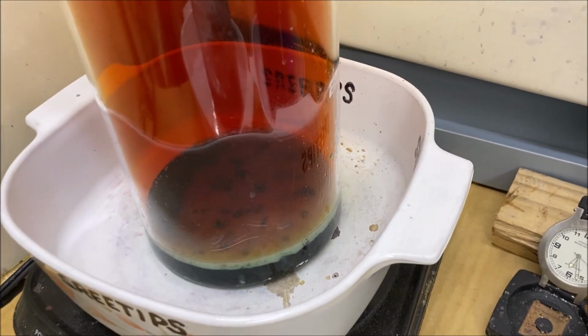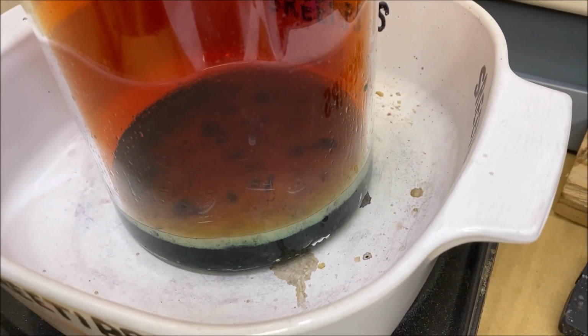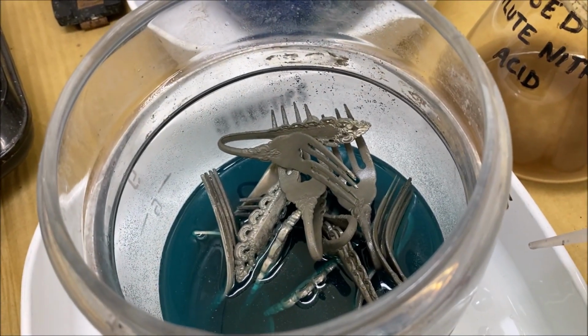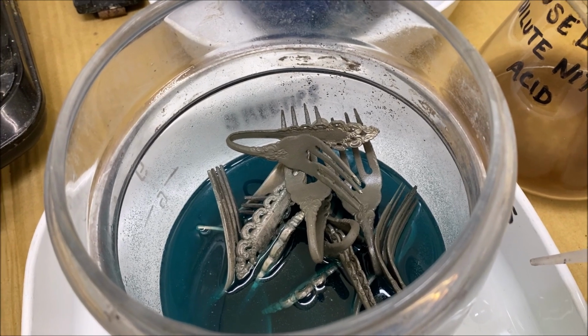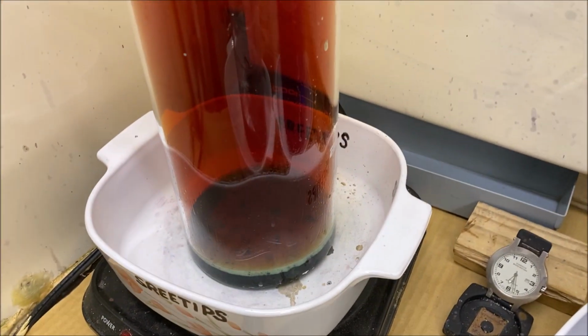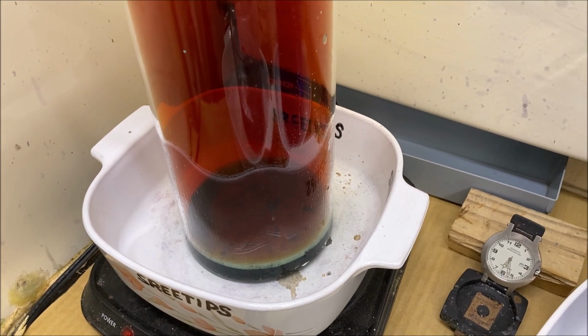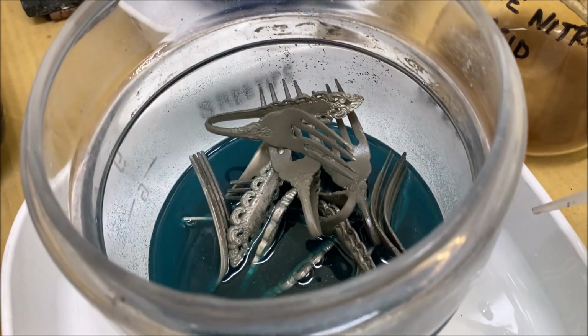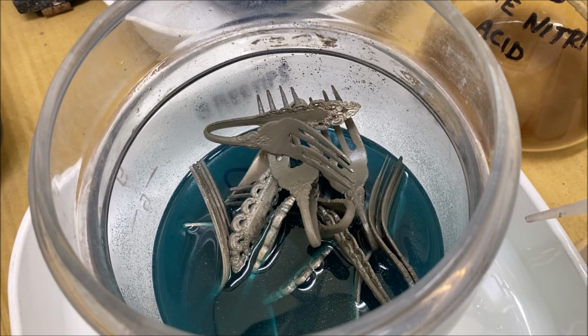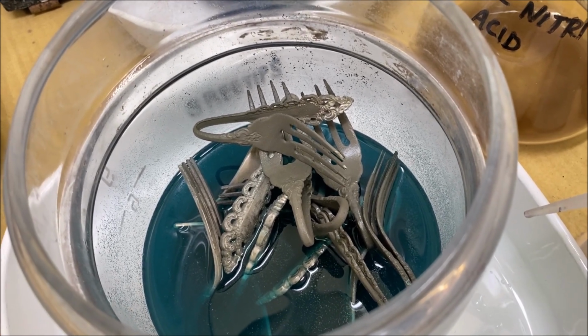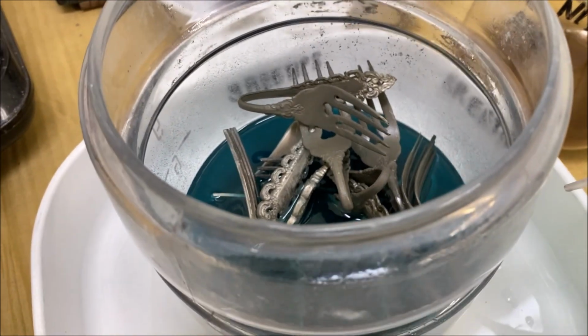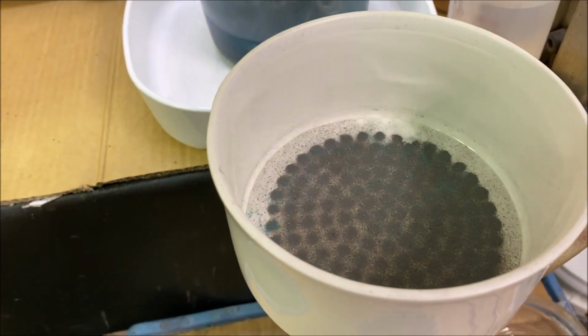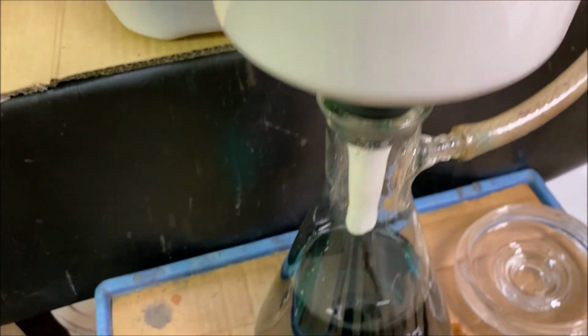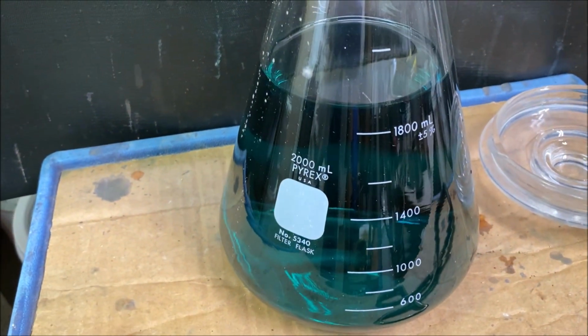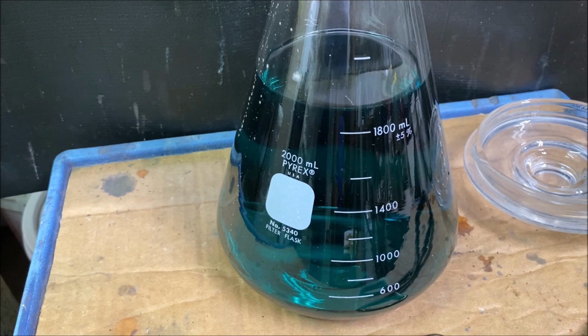I take that silver solution and I add it to this jar. I've got some sterling silver in here. Any remaining nitric acid in that solution will react with the silver in this jar and put that silver in solution. And then what I do is I pour it through a filter and I get a solution that's full of silver.